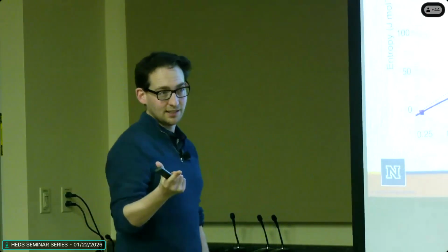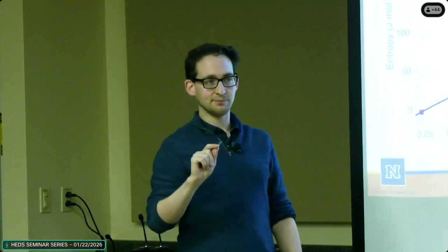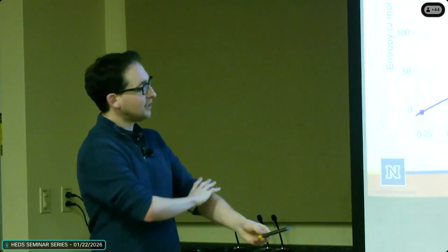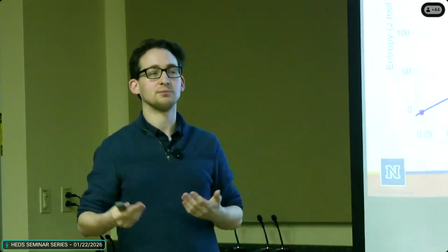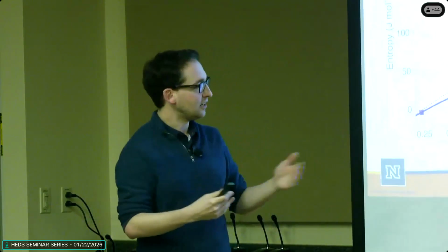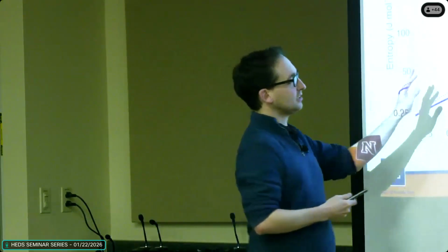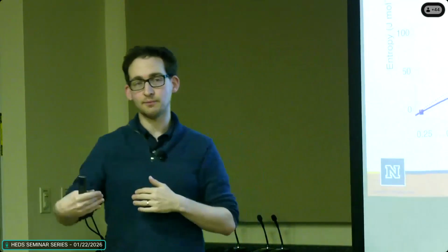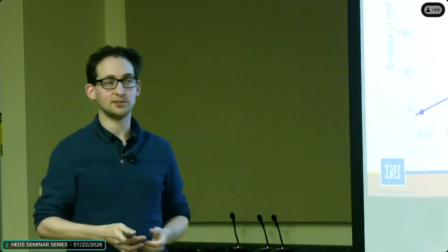There's a great theory of what the entropy of a gas does at high temperature and the entropy of a solid. They become essentially the number of degrees of freedom over 2 times R. So the solid has 6 degrees of freedom and the gas has 3. So you know what they are in this limit. But the liquid is sort of a mess, and it's a well-known problem of what the entropy or the heat capacity of a liquid is and how it changes as you go through these temperatures. So whether these 2 lines cross at all, I think, depends on the functional form of the liquid entropy or the liquid heat capacity across the temperature range. And that's not known. I don't think it's universal, for sure.